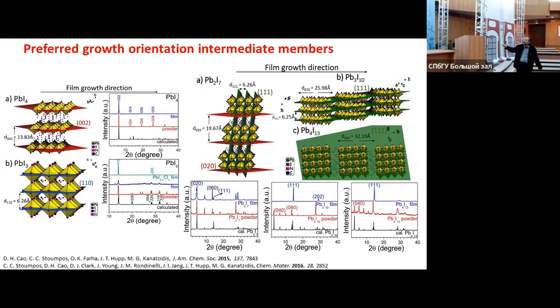But when you start thickening the perovskite, you get some different orientation also appearing. So instead of laying flat, you get some flat component and some perpendicular component. But when you go to 3 layers, you only see the perpendicular component. So basically, the layers are growing perpendicular to the substrate. That's interesting and useful because you extend the lattice from electrode to electrode. This is where you want to be. Why this is happening is still unclear, but it's certainly beneficial to make devices.